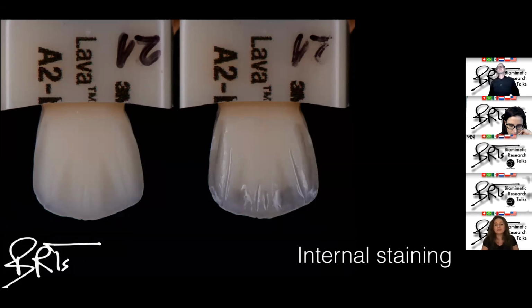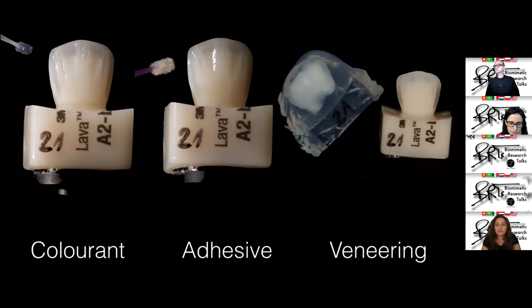with the groups that we followed with staining, we made just a little bit of stain on the incisal edges of blue mixed with lavender from GC OptiGlaze Colors. That's our mix for giving a little bit of this translucency on the incisal edge. And the protocol followed regarding the group with stains was sandblasting with Rocatec, then ultrasound cleaning, silane application, twice for 20 seconds, air dry, then heat dry at 100 degrees for 1 minute.